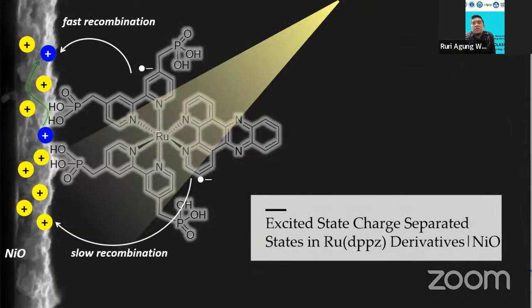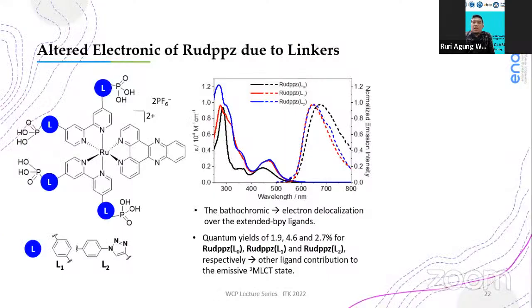Having discussed the electrode materials, now we shift our discussion to the dynamics of the charge separation at the ruthenium sensitizer and nickel oxide interface. So as mentioned earlier, we employed ruthenium polypyridyl complexes with dipyridophenazine, or DPPZ, ancillary ligands. Here, the bipyridine anchoring ligands are extended with conjugated linkers, that is phenylene and phenylene triazoles. As we see in the absorption properties, putting conjugated linkers shifts the visible absorption to the red, indicating electron delocalization on the extended bipyridine ligand.